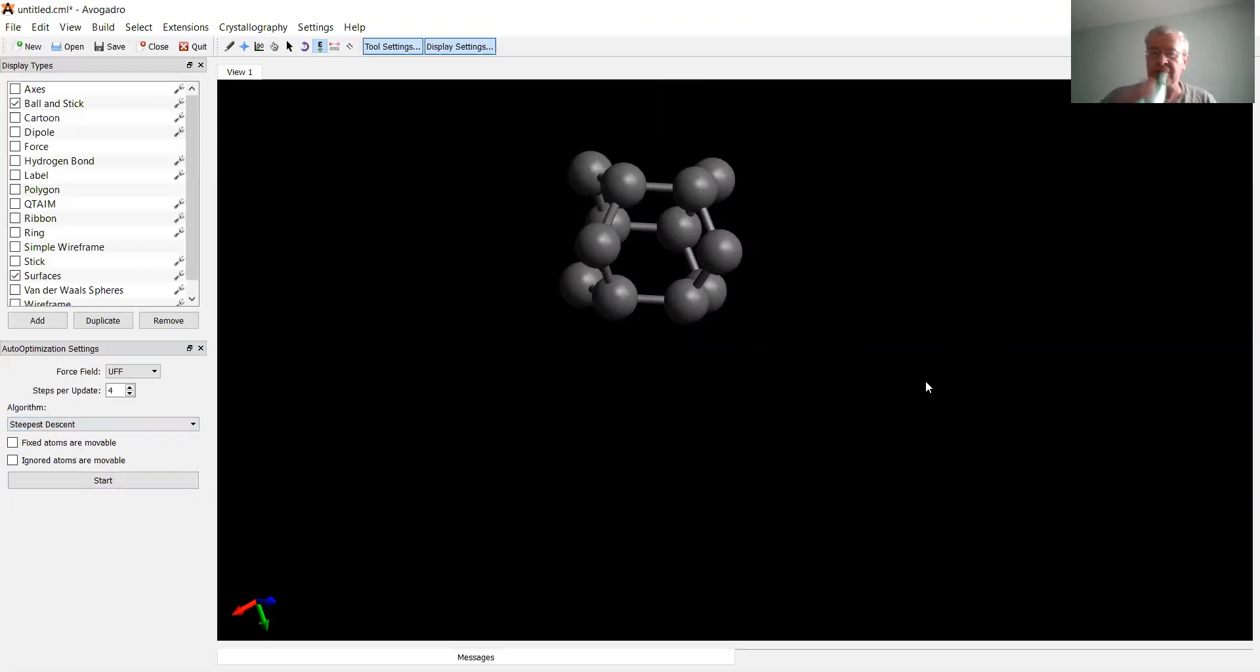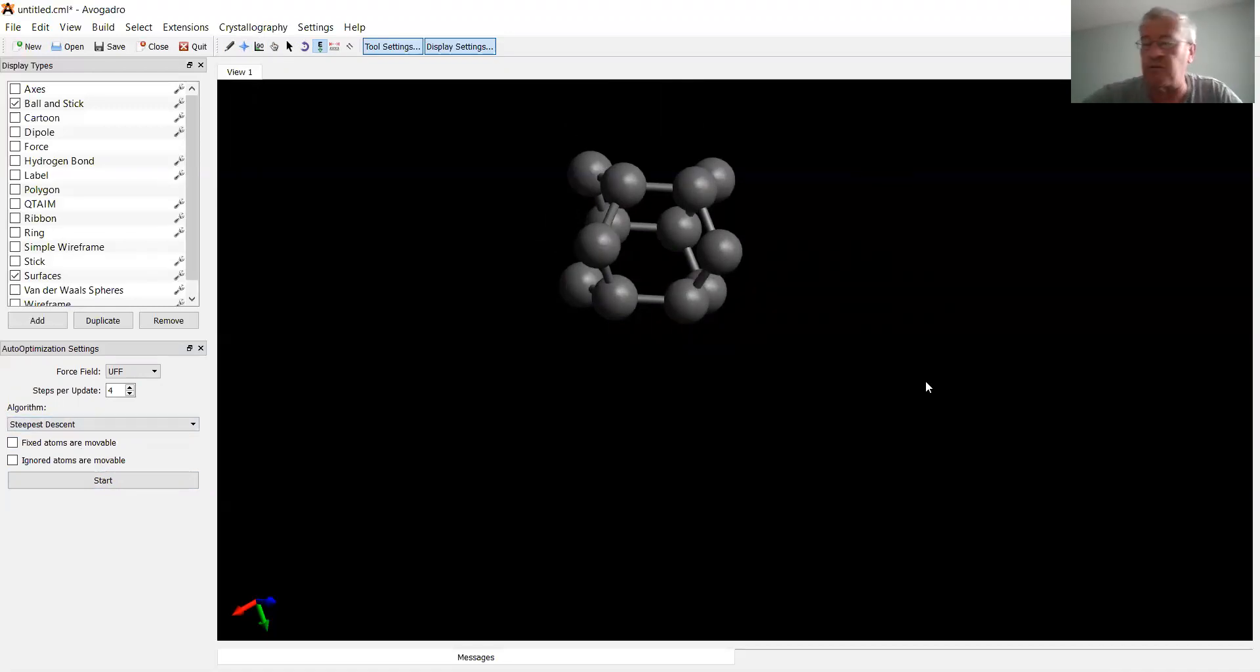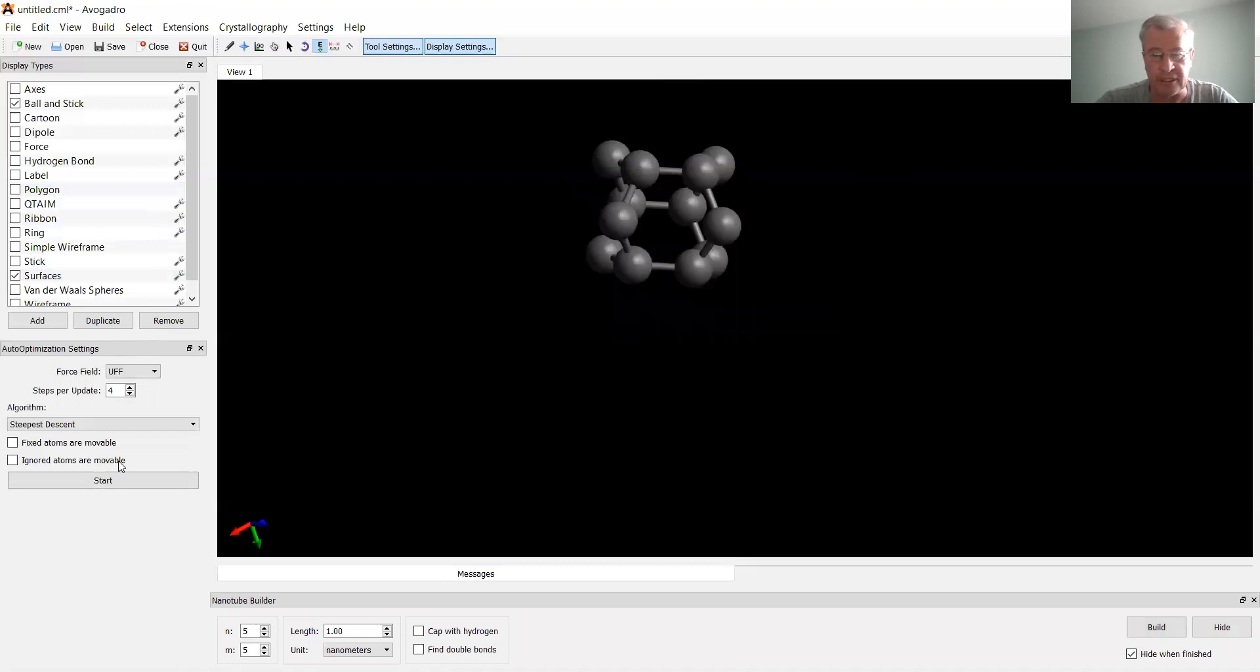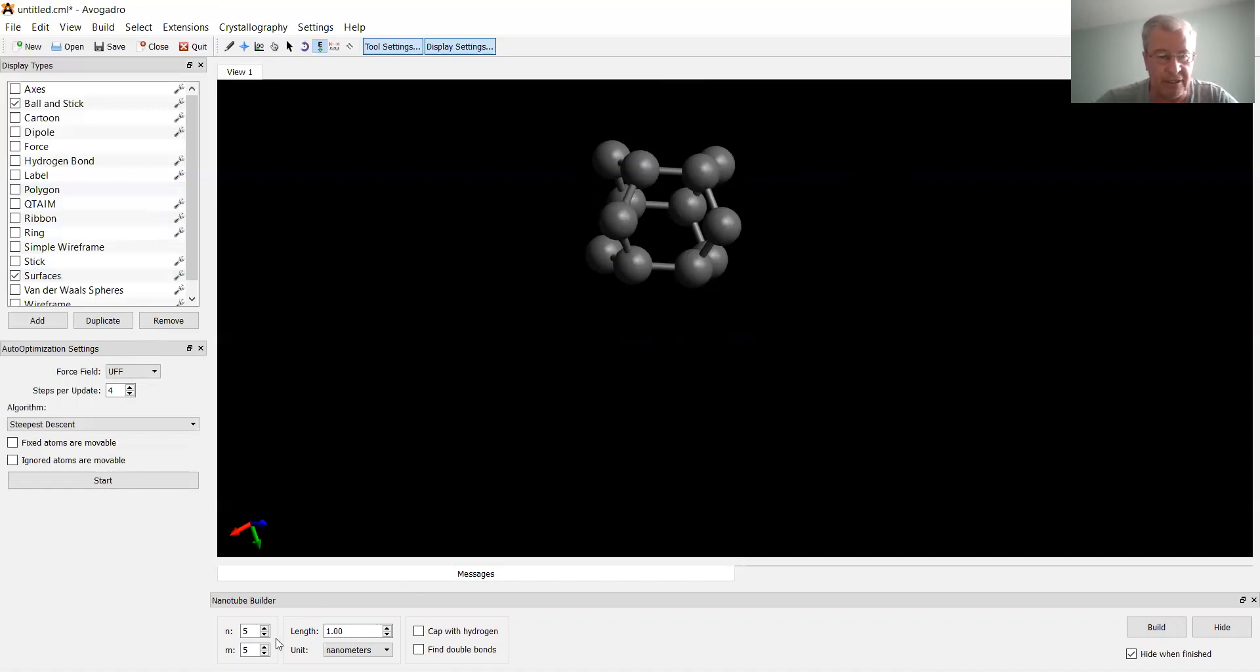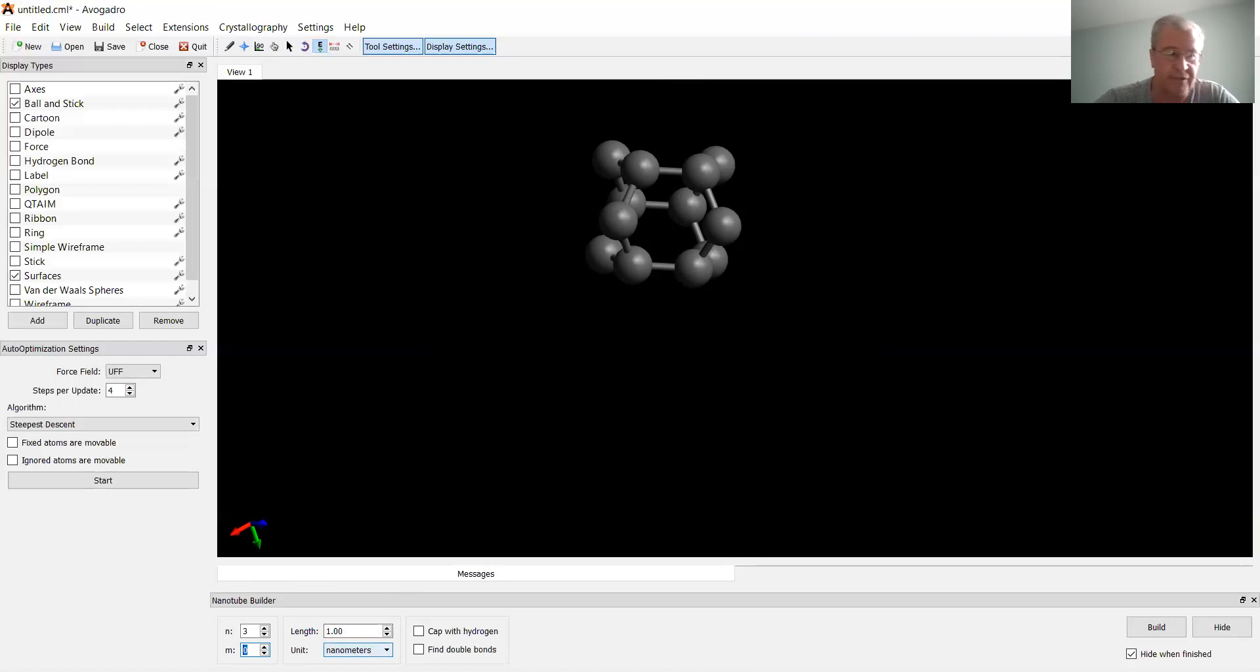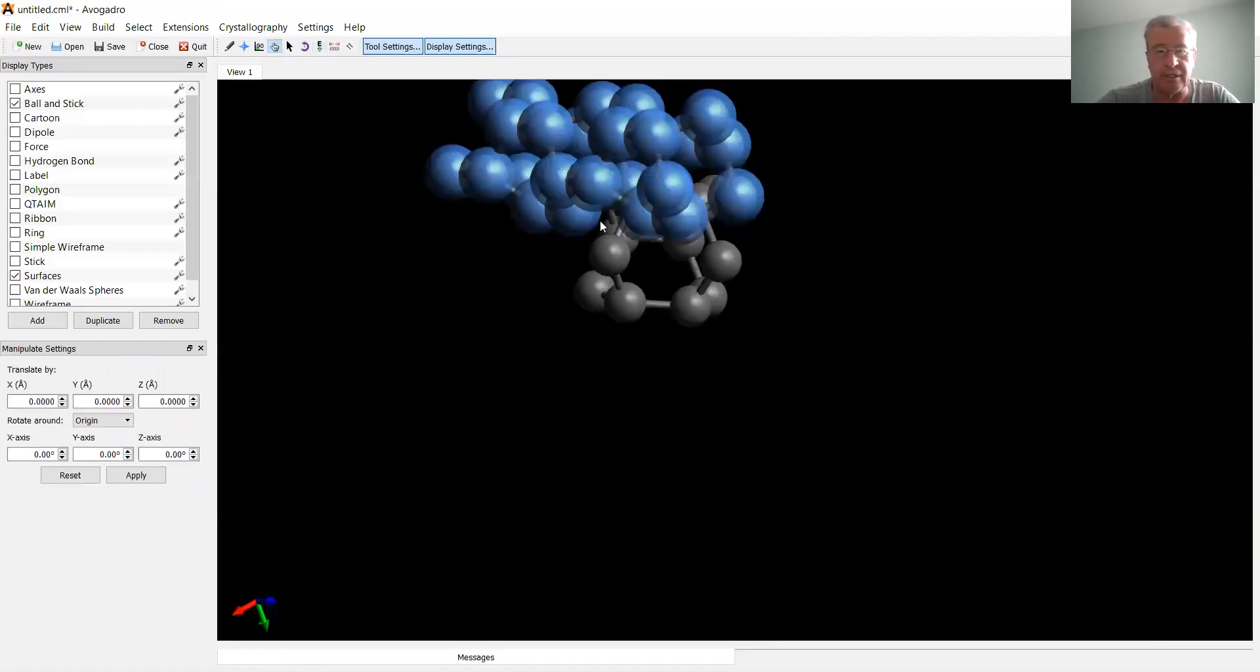However, the Avogadro program has a special carbon nanotube builder which I will be using to build a carbon nanotube. So I go here. There is a small menu here. So to make this same or similar nanotube, I select one of these numbers which are called chirality numbers. Three, another one will be zero. So that means that this nanotube will be made from three six-membered rings. I selected the tube one nanometer long. You can select different lengths. And build one.